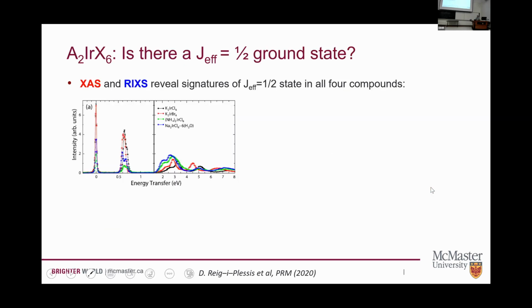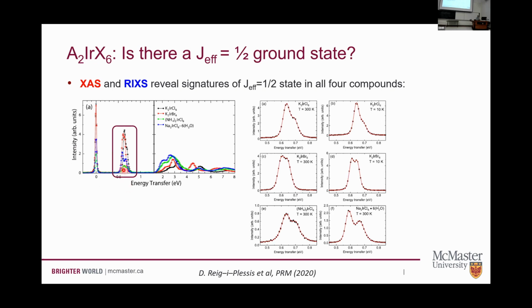Okay, so again, large branching ratio for all of these. Good sign for J effective 1/2 physics. What's really interesting is if we look at the RIXS and we focus on the t2g excitations here, this looks like one little peak, so we have to blow it up and look more closely. One of the things that's remarkable here is that the non-cubic crystal field splitting is very, very small. Okay, and it's very small even when we start to intercalate this system or when we play around with the size of the structural distortions.